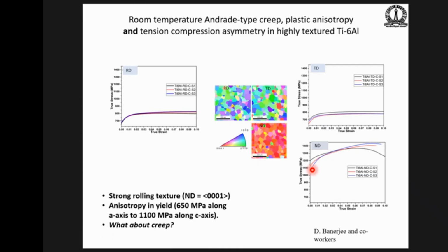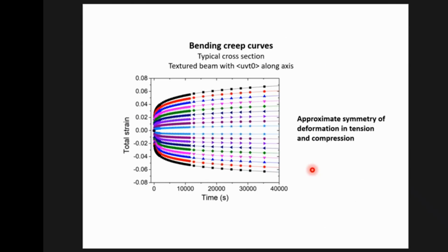Now the question is, what about creep? Bending is ideal here because when you have rolled plate, it's very hard to get samples perpendicular to the rolling direction, along the thickness direction. But we'll start with the rolling direction. And what you find is that it's nice and symmetric. This is reassuring. Everything above the midway point, this is the neutral axis. Everything above here is in tension, and this is in compression. So this is just a creep test at room temperature and measuring strains using digital image correlation.